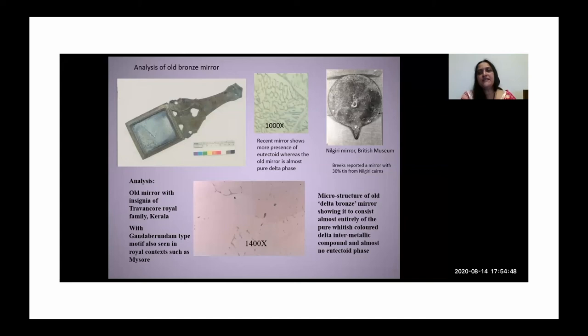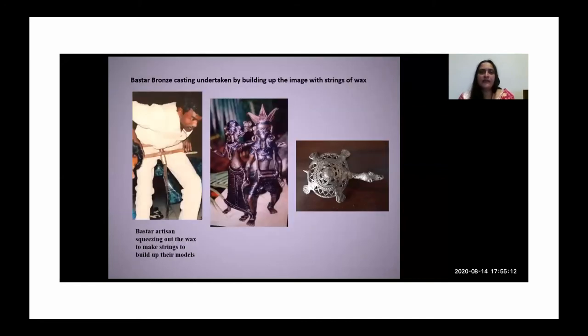But what is interesting is that at least there is some sort of longer standing tradition of using bronzes of around 30% tin in the past. Though, of course, the Aranmula mirror is more typically what I call the delta phase, which falls between 32 to 33% in bronze mirror. But still there are some elements of continuity and so on.